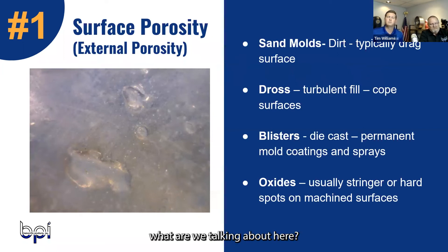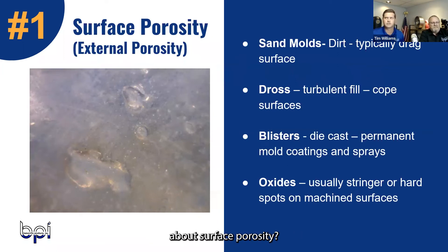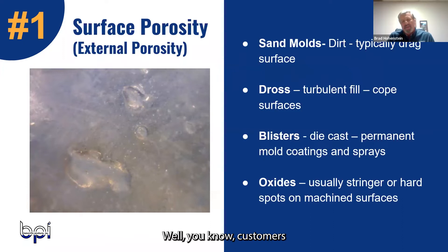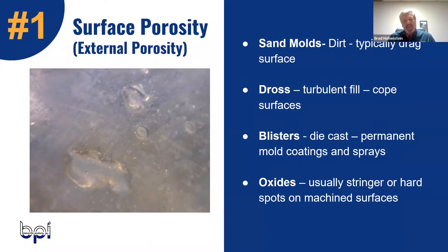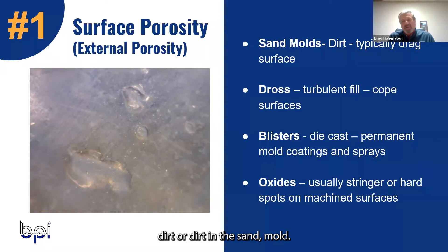Brad, so what are we talking about here when we're talking about surface porosity? Customers call almost all defects porosity. What we're looking at here is some blisters on this slide where it's flaked away — dirt in the sand mold.